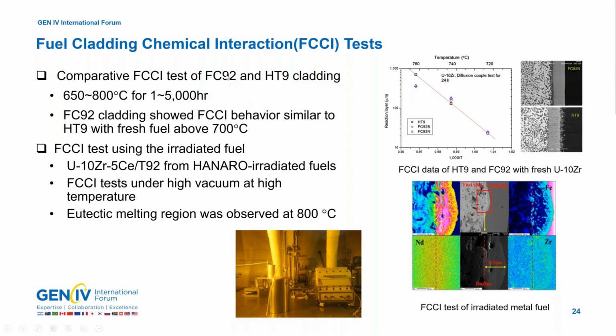For those claddings, FC92 and HT9, HT9 has about 12 chromium content and FC92 has 9. To check whether there is any difference in the chemical interaction behavior, we did some comparison tests with the pures, and found there was no specific difference between these claddings.